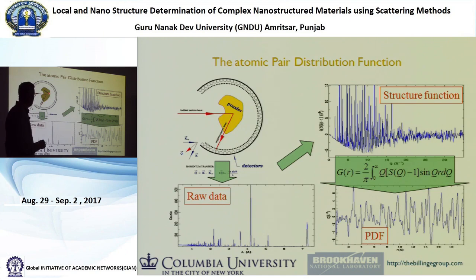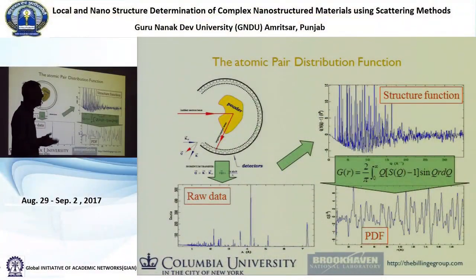What we do is we take our powder of nanoparticles and we put it in the beam. And then we select data as a function of scattering angle, and we get the powder pattern. So this was a crystalline material, so it actually has Bragg peaks in it. But this is raw data, so it has experimental artifacts in it, and it has not been properly normalized.